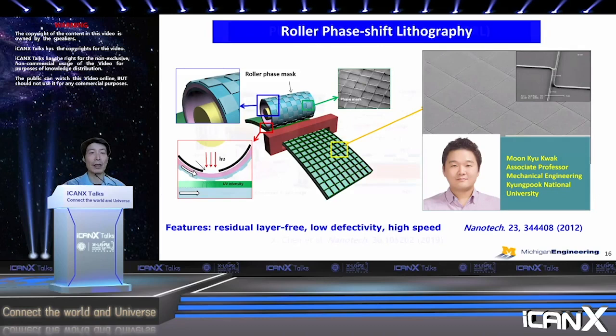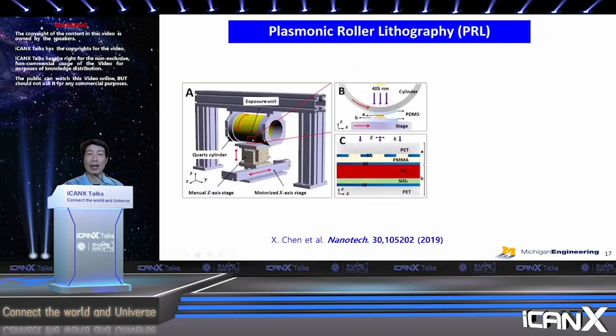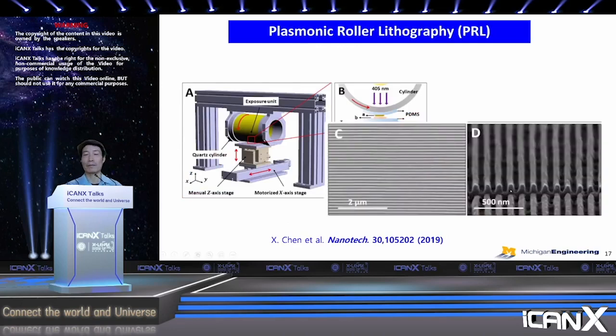Now, coming back to this plasmonic aspect. This is the setup we're using. We have this special mask wrapping around the quartz tube, and the substrate is on a moving stage. If you do things properly, you can actually get it done. So you can do it in a continuous fashion and get these deep submicron structures.